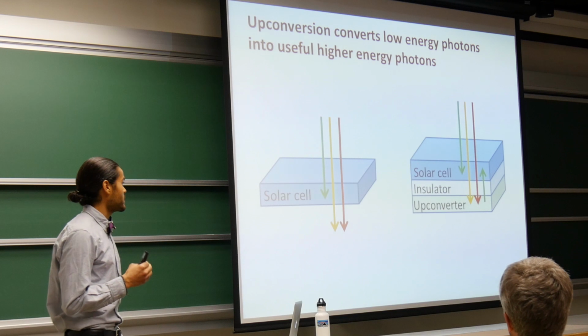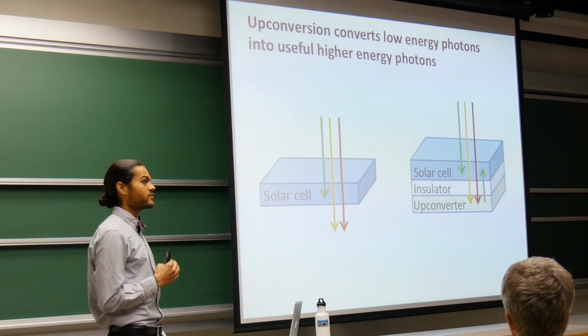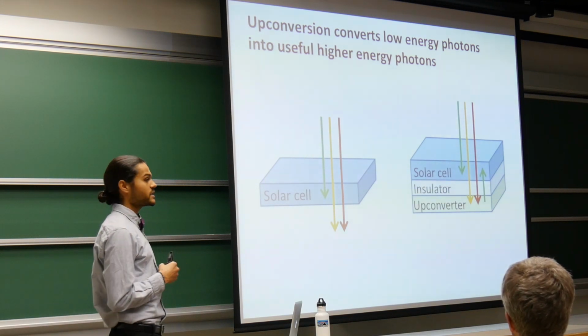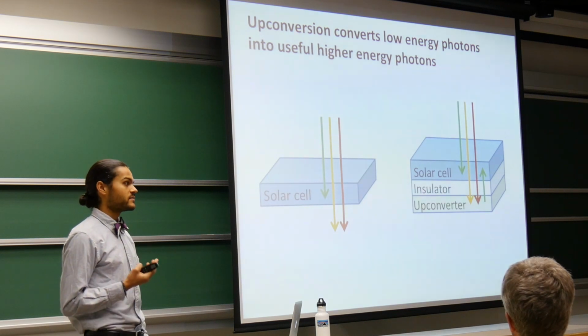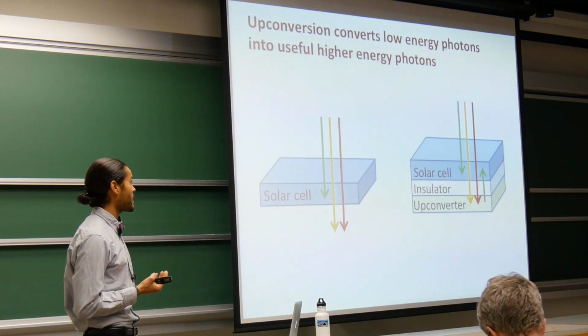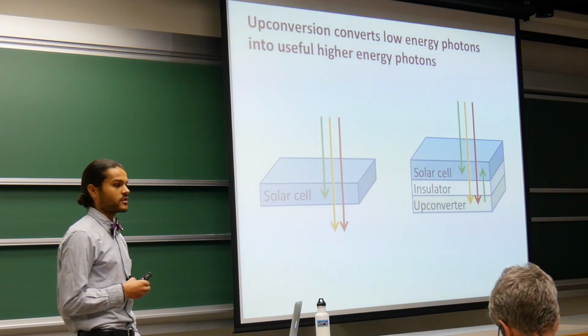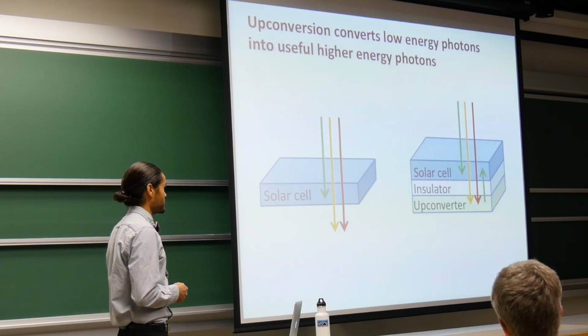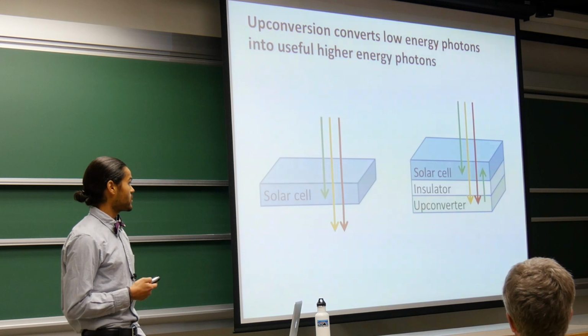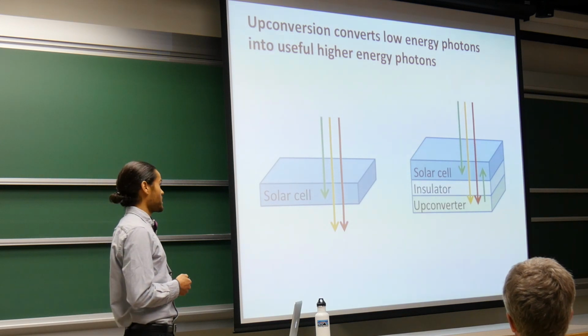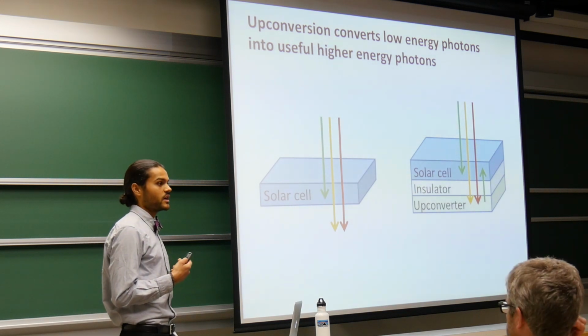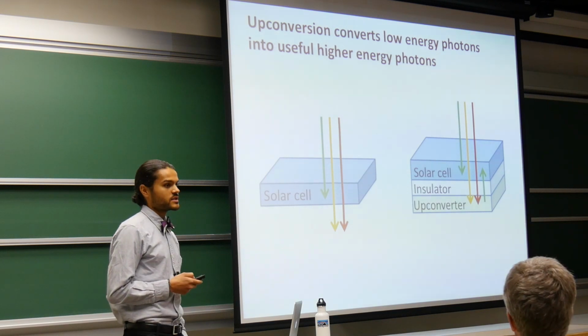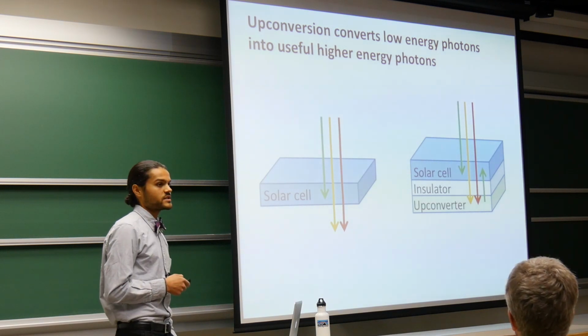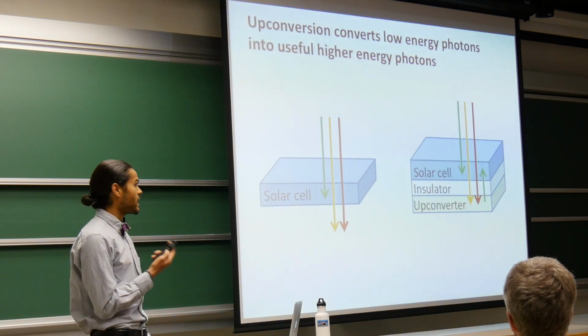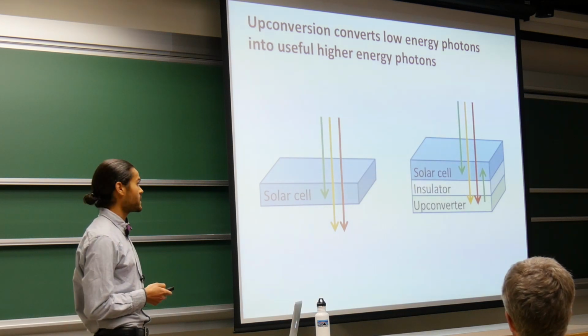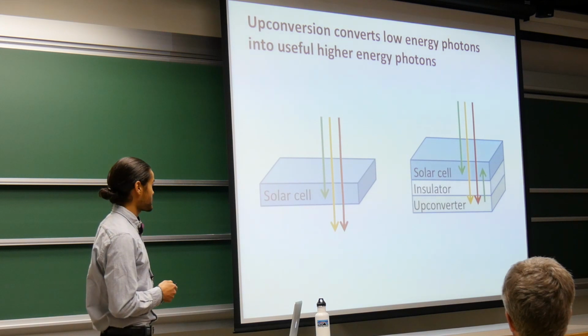I should mention that in this design, the upconverter is isolated from the solar cell above it. And so unlike a multi-junction cell, which requires very expensive lattice matching as well as difficult current matching conditions, the upconverter does not require those particular things. Also, in comparison to an intermediate band solar cell, the upconverter doesn't introduce extra non-radiative recombination sites to diminish the efficiency of the solar cell. And so essentially you can optimize the solar cell and upconverter separately in order to create the most efficient device.